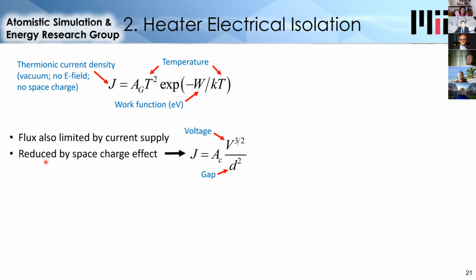And like I said, the emission is also reduced by the space charge effect, which there's another equation called Child's law, which estimates this effect, where the current density is equal to a relationship between the voltage and the distance between the heater and the thing it's arcing to, which is the insulation. So this gap is about an inch. Because this gap is quite large, this equation predicts a current density of only 0.1 amps for this size heater. And so really what we get is something between the two, but it just shows that neither of these equations are really completely valid for our situation because we have a gas present.